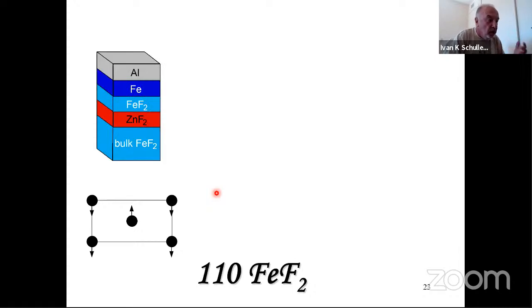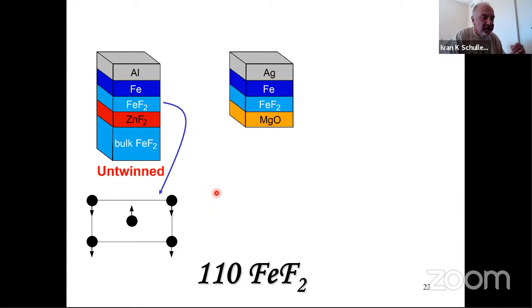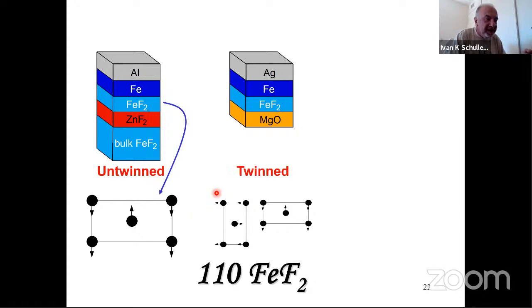Now what happens? If you grow this material on a bulk FeF2, you put some zinc fluoride, which is non-magnetic, you grow this FeF2, and you grow this exchange bias iron on top of it, you have this structure. So that's the structure at the interface. You can grow this differently. It's called an untwinned structure, a single crystalline structure. You can grow this FeF2 on top of magnesium oxide. And then if you grow it on top of magnesium oxide, there are two possible orientations as shown next to my laser pointer there. This is called a twin.